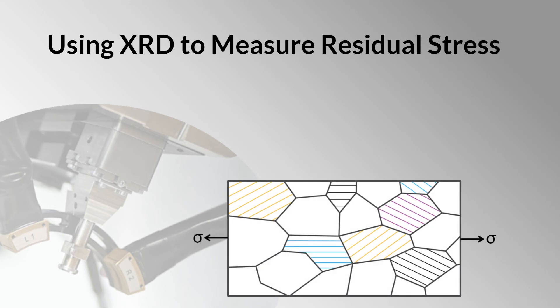First, we measure the Bragg angles of diffracting planes over a range of orientations by scanning Psi, which is the angle between the sample surface and the diffracting plane.